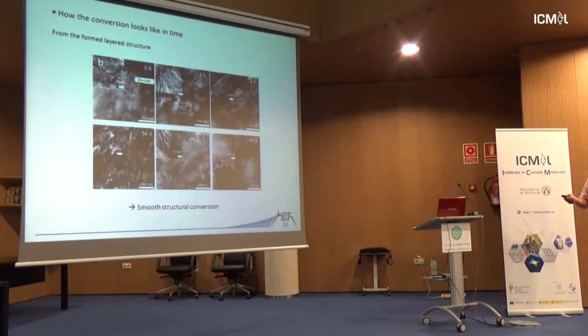And you can see that from the layer structure. At 0, at the starting point, you already have a layer structure, so that's LSH, with a very small lateral size. And little by little, the lateral size dimension is growing up. And you can see all this. And at the end, you have the LDH.